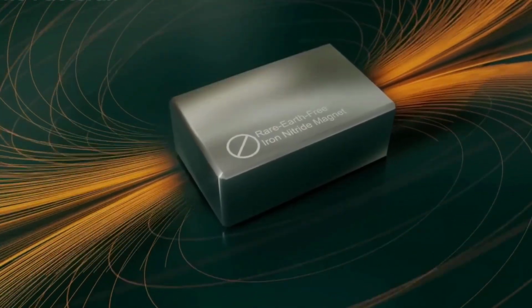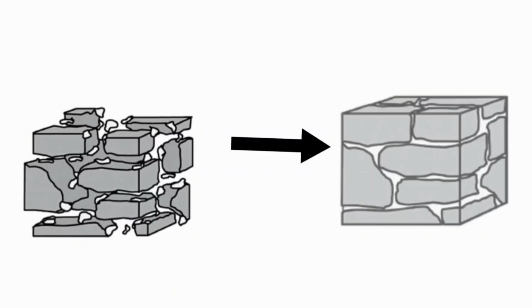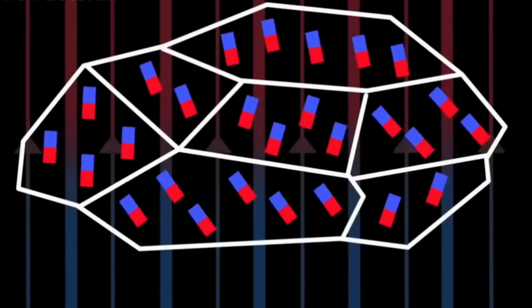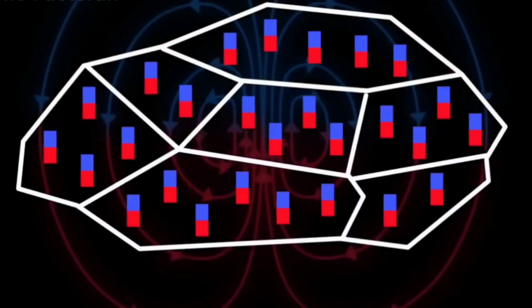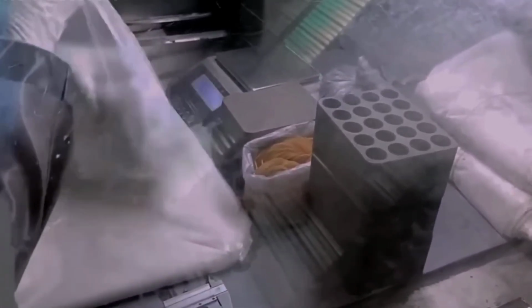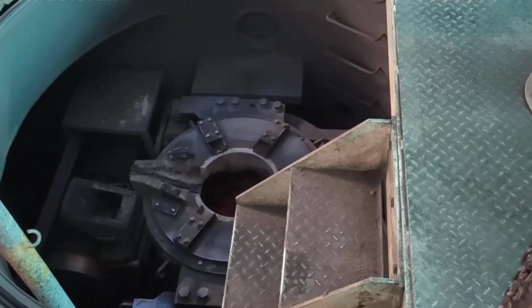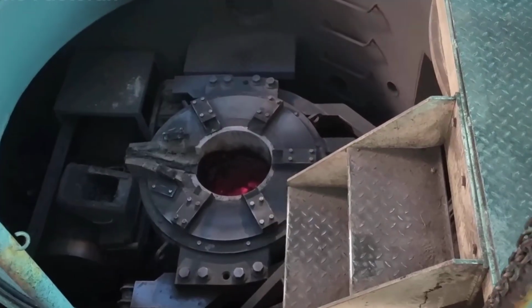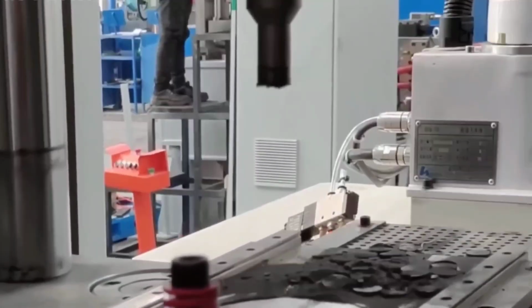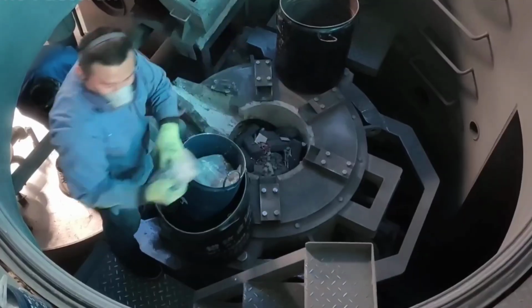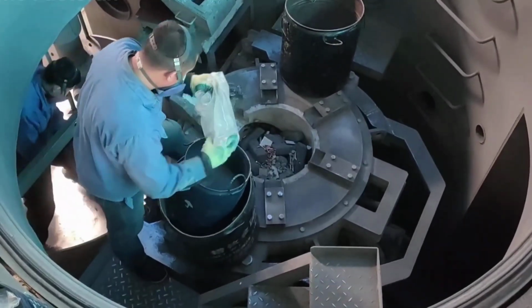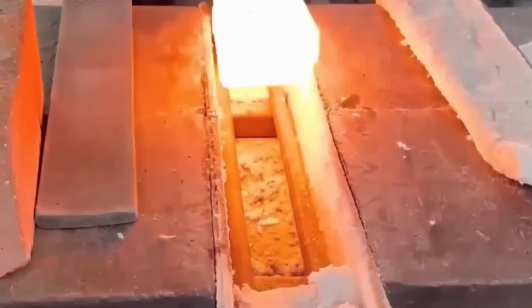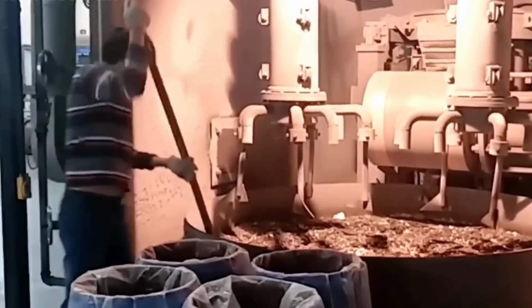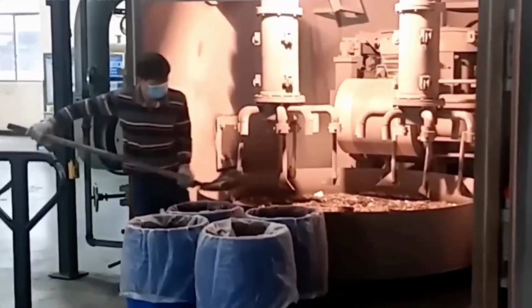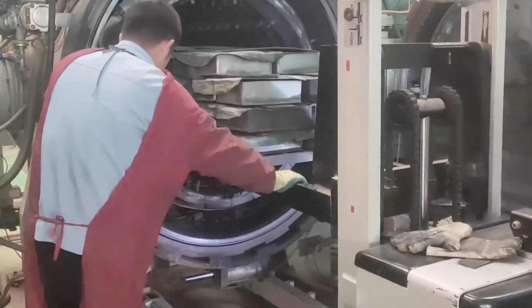For the next 4 to 5 hours, the system maintains a stable temperature, allowing the alloy particles to compact tightly and eliminate even the tiniest voids between them. During this phase, the material transitions from a porous form to a fully dense solid, reaching nearly 100% of the density of bulk metal. And once the desired equilibrium is achieved, the temperature is slowly reduced over several hours, degree by degree, giving the crystal structure time to lock in the previously aligned magnetic orientation. Finally, an additional heat treatment at around 950 degrees Fahrenheit stabilizes the entire structure, completing the sintering process.